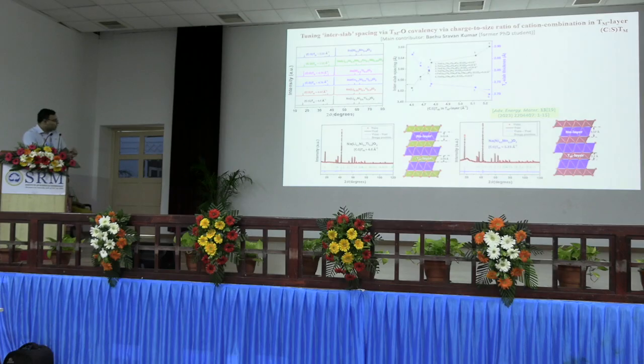We designed and developed a few model layer transition metal oxide materials. Now what we saw is that when the charge to size ratio in the transition metal layer is lower, I indeed have a narrower interslab spacing, which means my sodium oxygen bond is shorter and hopefully stronger.